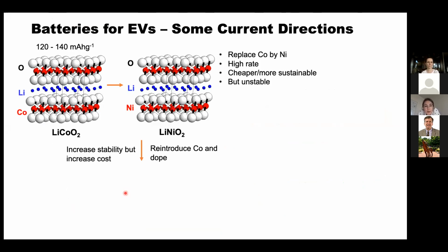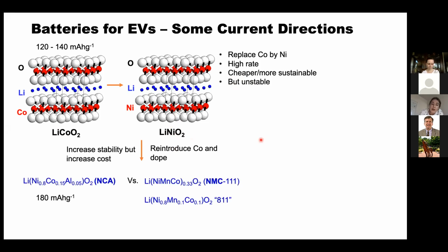So just to give a sense of where we're going, if you talk about the lithium cobalt oxide system, the push in electric vehicles is to move away from the more costly and unsustainable cobalt oxide into the lithium nickel oxides, but that then brings issues in terms of instabilities at high oxidation states. So nickel, when you remove all the lithium, becomes nickel 4+, and nickel 4+ is not very stable with respect to losing oxygen. And so what the field does is to reintroduce the cobalt and then dope with other elements to increase the stability of the system.